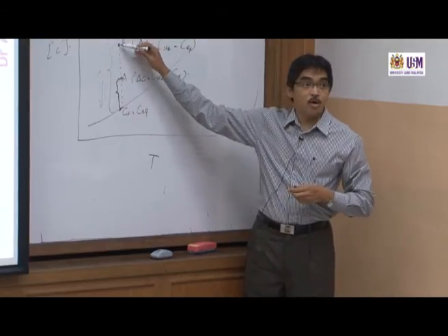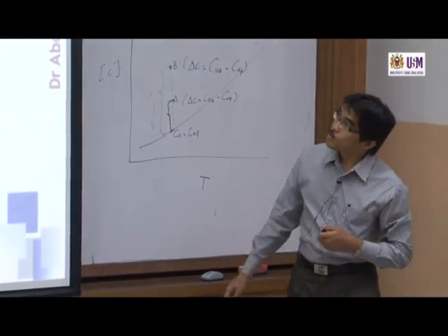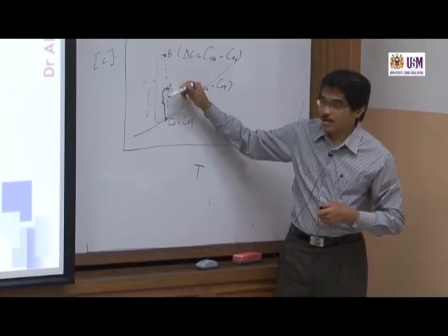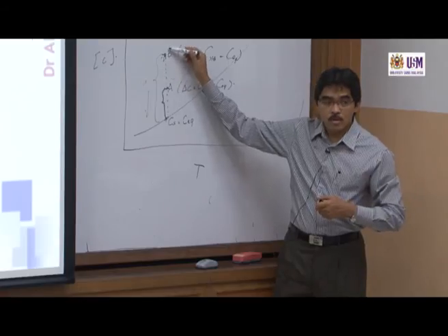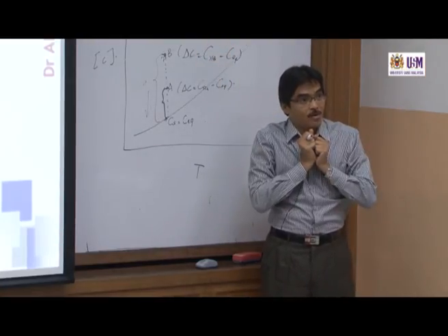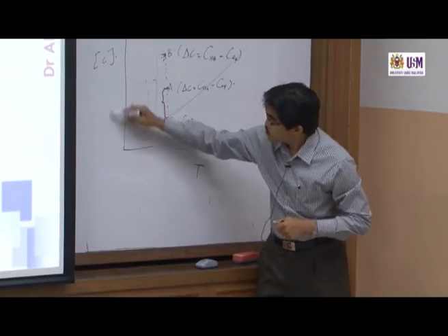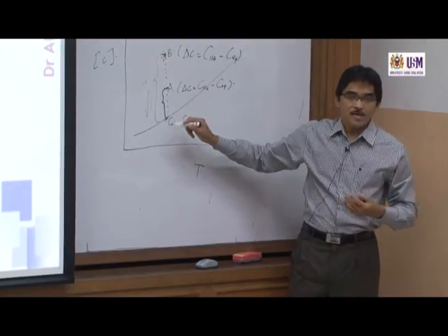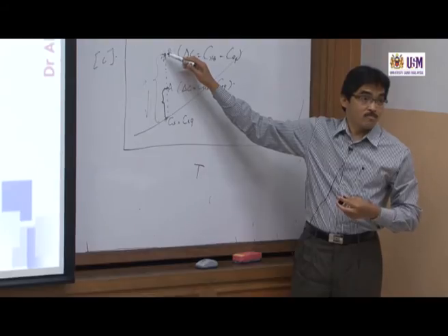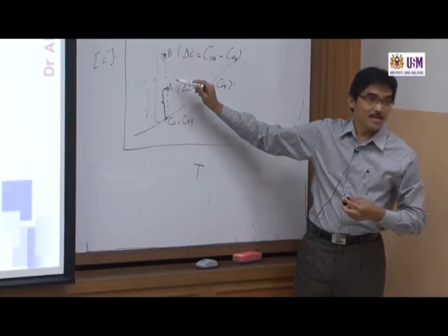If we start the nucleation at point B, which is higher than point A, the remaining supersaturation is from this point up to that point, which is much higher. So the concentration now would decrease because more free molecules form crystal. So the amount of free molecules in the solution reduces because they form crystal. So the concentration would decrease up to this point, where equilibrium stops. So now if we start the crystallization nucleation at point B, we get more solid crystal phase volume compared to if we start the nucleation at point A. Okay? So that is the meaning.